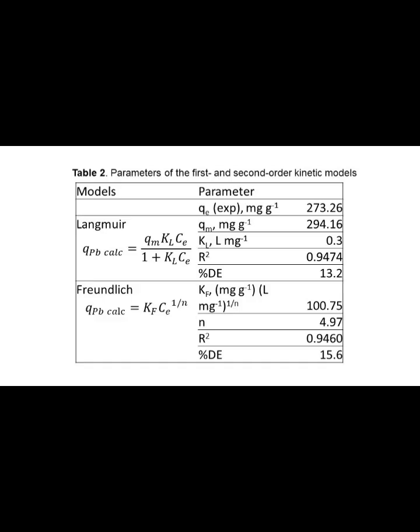The R2 and %D values indicate that the Langmuir model provides the best fit to the experimental data. The good agreement with the Langmuir model suggests a chemisorption process, considering that this model assumes a rate-limiting step involving specific chemical interactions between adsorbate and adsorbent.